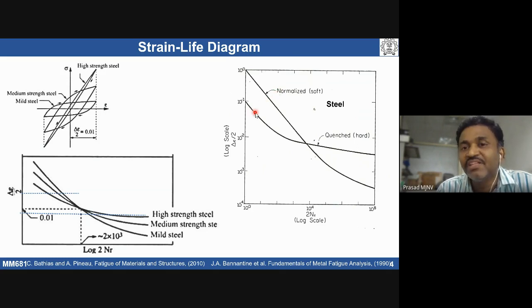At the same time, the crack propagation is going to be fast in case of hardened steels as compared to normal steels, because significant plastic deformation takes place that can blunt the cracks. Okay, you will understand soon.